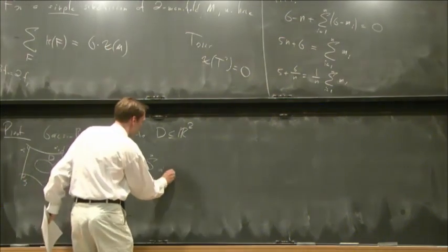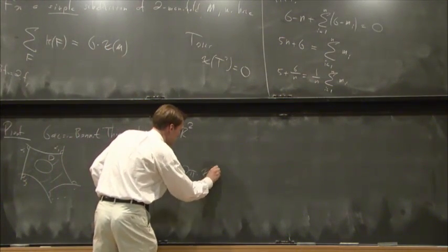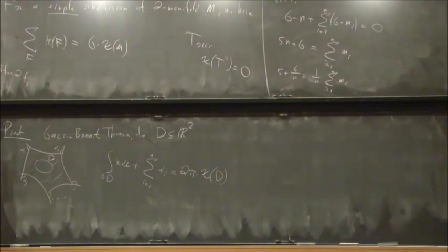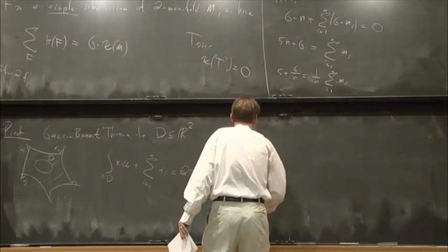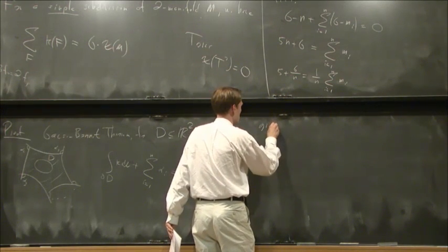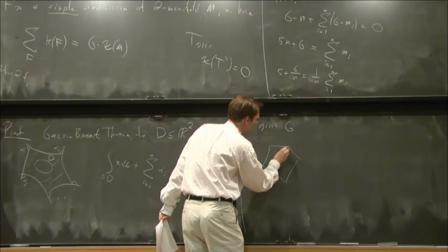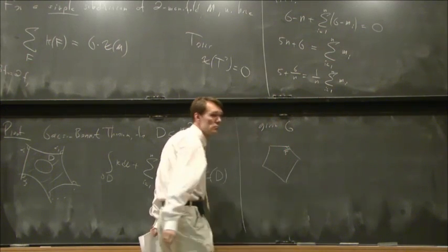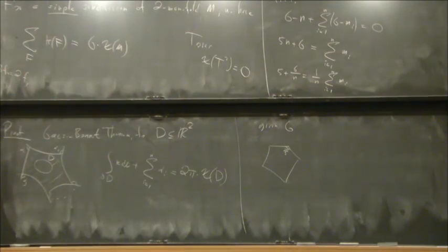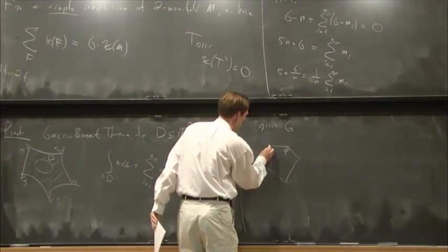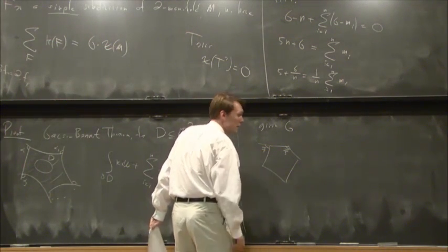This is 2 pi times the Euler characteristic of the region D. So this is Gauss-Bonnet in the plane. Well, now when I apply this to a grain, the thing to remember about the grain is that all these angles here are 2 pi over 3. All nicely in this application, they all come together in nice 120 degrees. So all the alpha i's here are pi over 3.